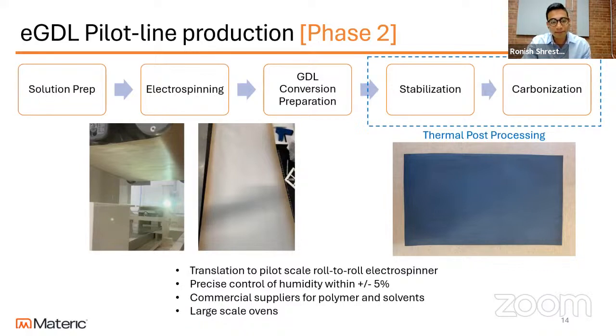For this particular formulation, we use dimethylformamide as a solvent, which is hygroscopic. So precise control of the humidity was very important because the solvent itself picks up moisture, in turn not letting it evaporate during the electrospinning process, which causes a lot of defects in the final fiber mat. We were able to translate from the lab scale to the pilot scale and produce rolls and rolls of this material. And this process also came with an added challenge of thermal post-processing.